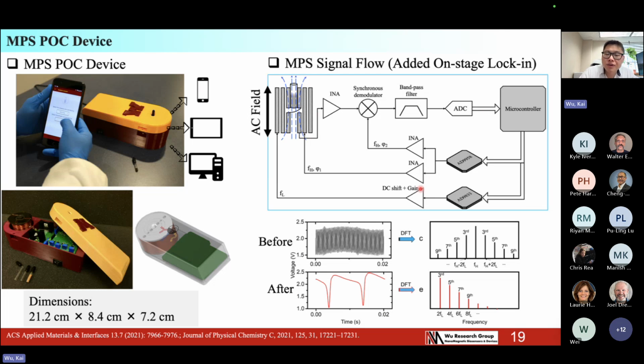So we showcase two different MPS platforms. One is where we apply a single drive field with frequency F to the nanoparticles. We will get the higher harmonics at 3F, 5F, 7F, these odd harmonics, from the particles' response. Or we can do the two frequency combination, one with high frequency, one with low frequency. This frequency modulation will modulate the higher harmonics around the FH component, which is usually 5 kHz. So we can collect the harmonics at FH plus minus 2FL as the third harmonic, and FH plus minus 4FL as the fifth harmonic from the nanoparticles' response. These slides show the POC device we built and the circuitry from signal generation to signal collection from the nanoparticles.